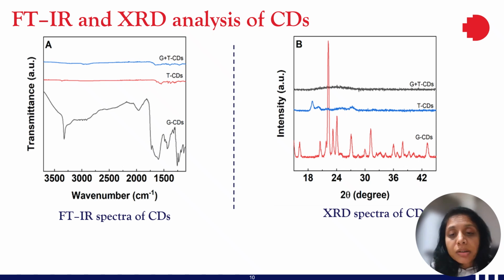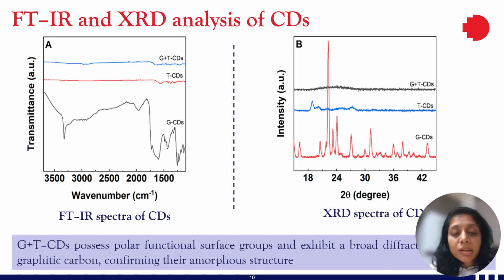And the XRD pattern displayed by glutamic acid and tryptophan carbon dots showed a weak and broad diffraction peak centered at 23.5 2 theta value, which corresponds to the 002 lattice plane, indicating the formation of a graphitic-like structure. And this result agrees with the calculated interplanar spacing from the high-resolution TEM image. So with this analysis, we could say that glutamic acid and tryptophan carbon dots possess polar functional surface groups and they exhibit a graphitic core structure.